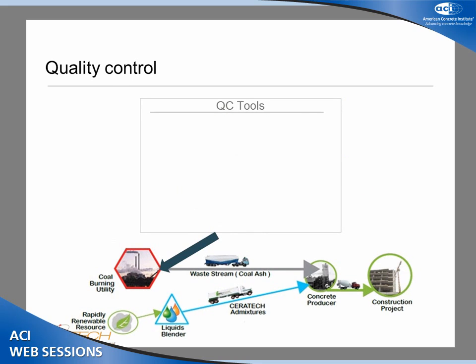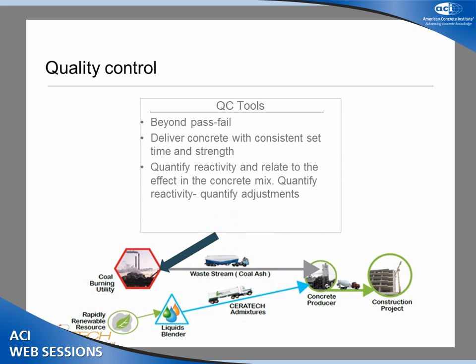So we were looking for quality control tools that we could actually set up at the power plant or before, basically, the ready-mix plant. So we need something, again, beyond pass or fail. We know that Class C works and Class F will not work for us. We want to be able to deliver concrete with consistent set time and strength. And by quantifying the reactivity, we can quantify changes also in the mix. So if we know how much the reactivity changed, we can quantify the amount of change that we have to make in our activators. So we could deliver not only a unique product, but we can deliver quality and we can deliver consistency.